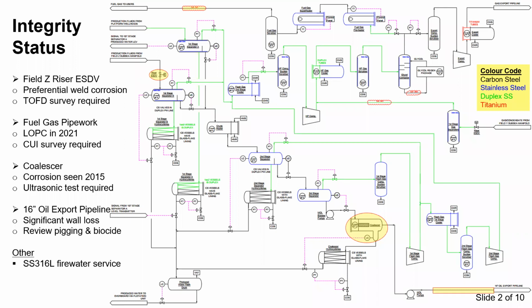Now onto the coalescer, which is just downstream of the third stage separator. Corrosion was identified internally within that vessel in 2015. A coating was applied. However, because there was only 1 millimetre left of corrosion allowance and it was suspected to be corroding at a rate of 0.2 millimetres per year, it's recommended that we do some ultrasonic testing to identify the wall thickness within that vessel and whether we believe that coating is actually providing sufficient protection.